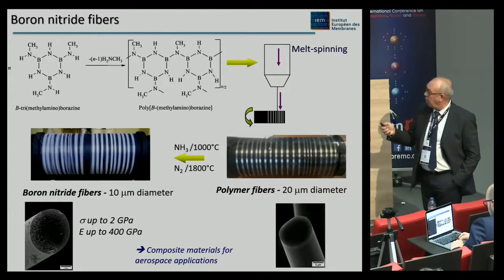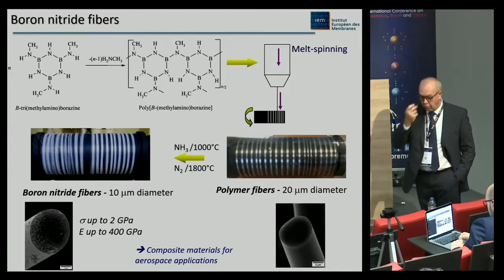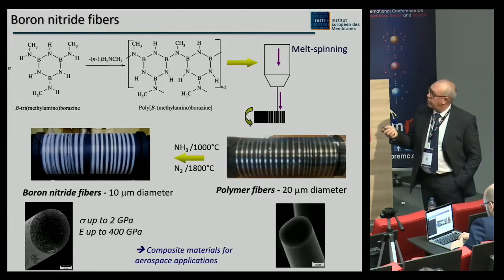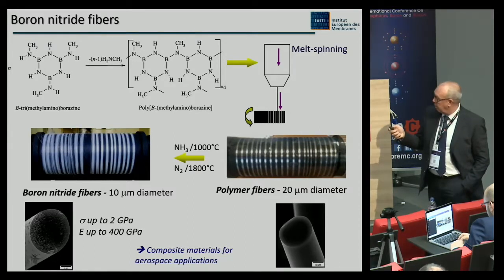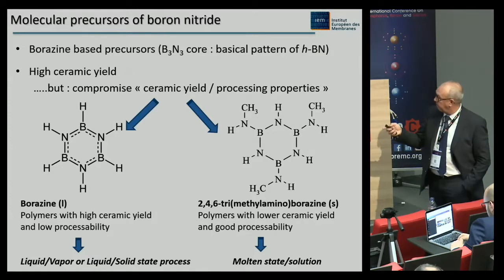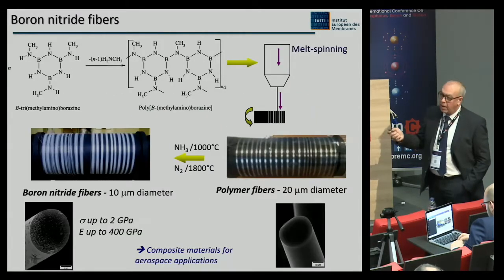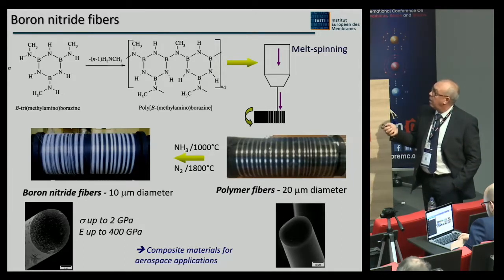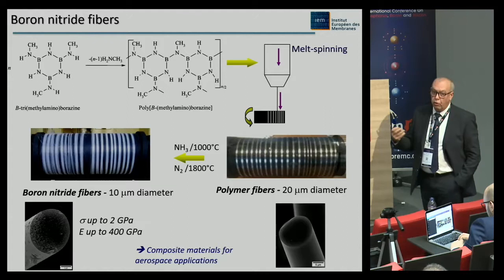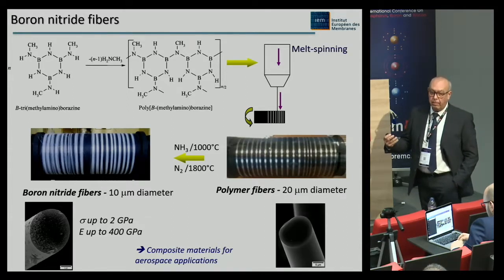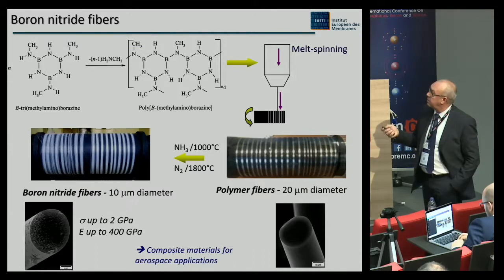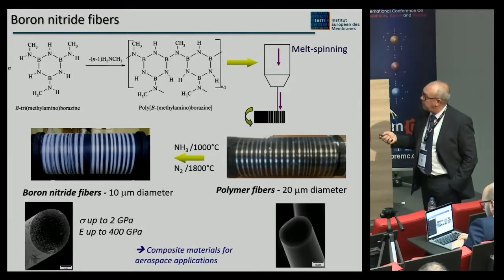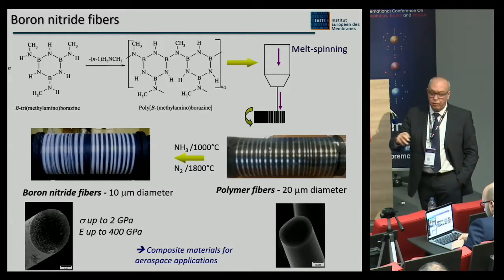As an example, a relatively old example we performed in the group is the preparation of boron nitride fibers. You take this tris(methylamino)borazine, the precursor I just described here. It's relatively easy to polymerize thermally to obtain this kind of polymer with N-methyl bridges between the rings. And this polymer displays good processing properties because it is fusible at around 180 degrees, and you can melt-spin this polymer into this very nice polymer fiber of about 20 microns in diameter. You have the SEM picture here; the fiber is very smooth with no defect.